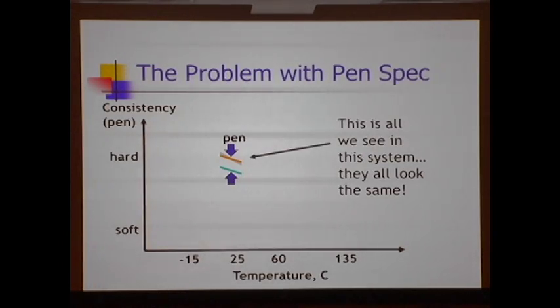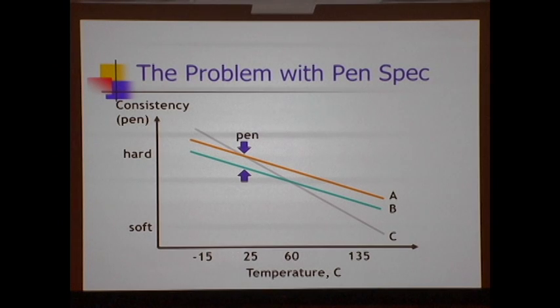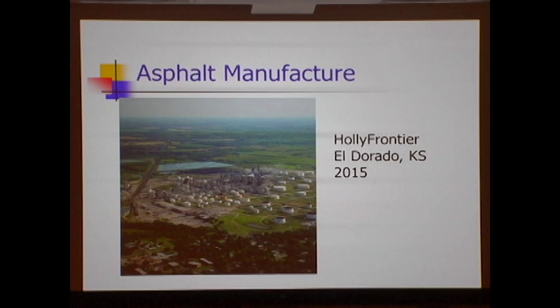There's a problem, though. When we run the penetration test, we're running it at only intermediate temperatures, at room temperature, basically 77 degrees Fahrenheit. And so all we're seeing in terms of the physical properties of that asphalt are its characteristics at that one temperature. And the problem is, if you look at what's going on with the asphalt at a multitude of temperatures, you can see that three asphalts, as in the example that I'm showing here, that have the same penetration grade can have very, very different properties at other temperatures, such as high construction temperatures over on the right, at high pavement temperatures, which is kind of in the middle, right above 60 degrees C, and at low temperatures on the left-hand side of the graph. So there were some limitations to the penetration specification, both in Texas and elsewhere.